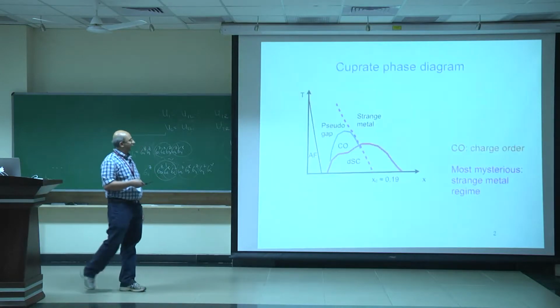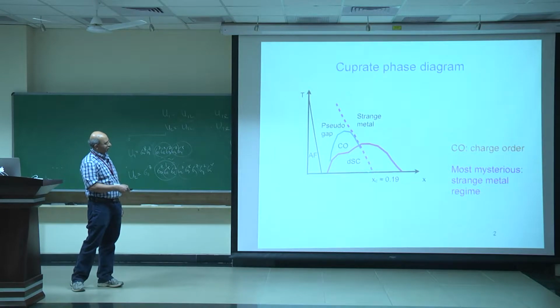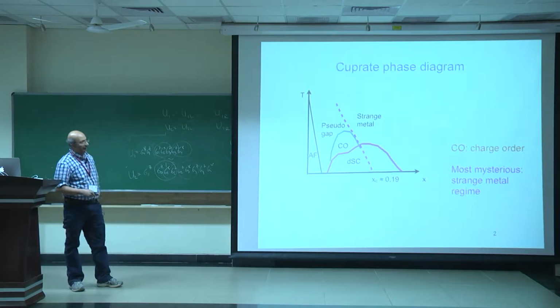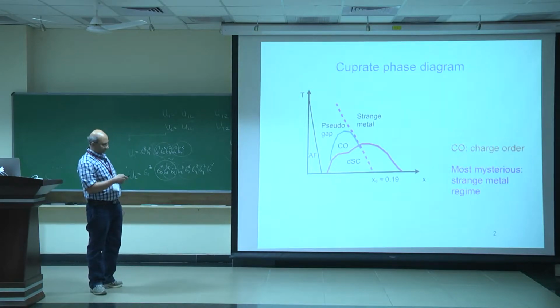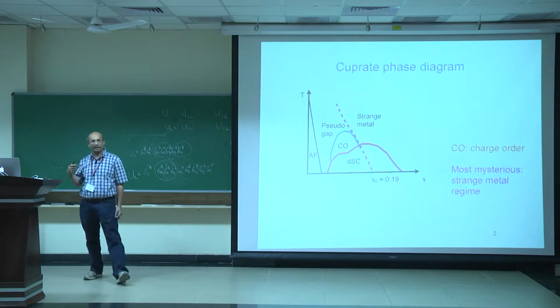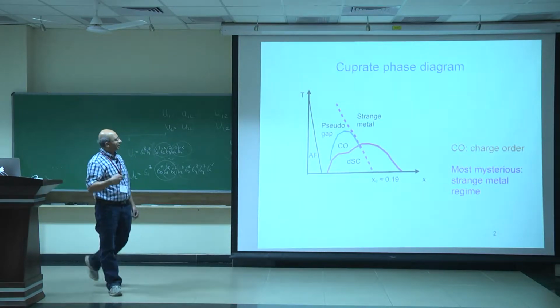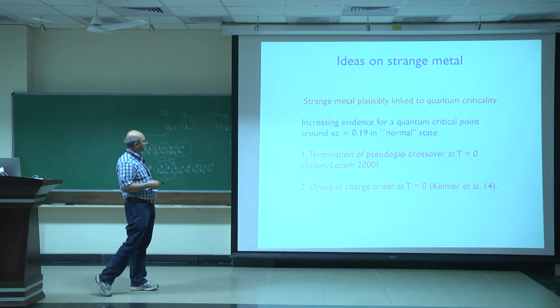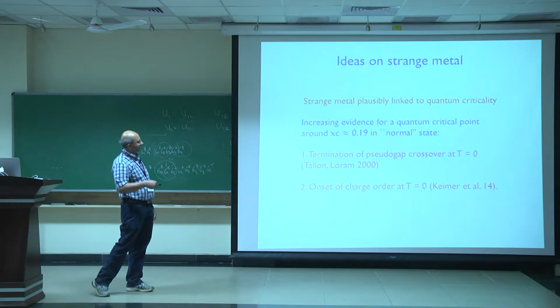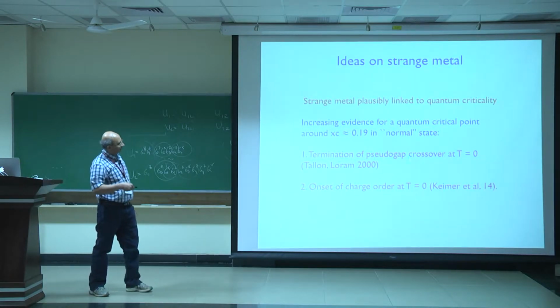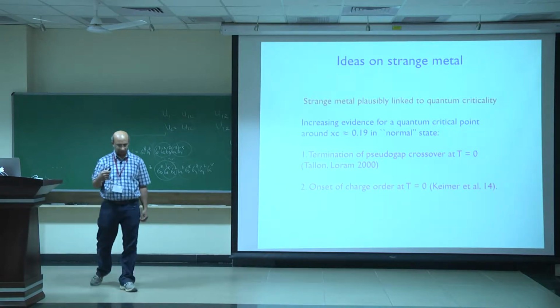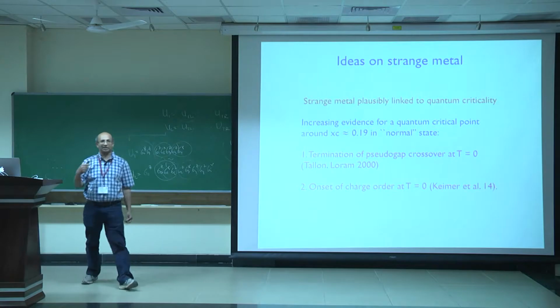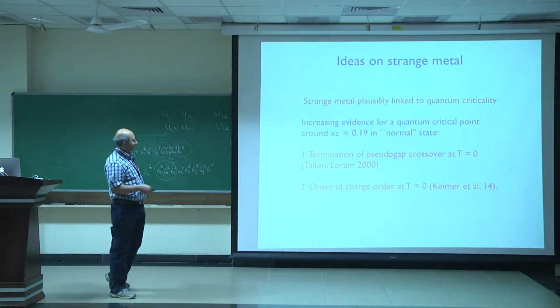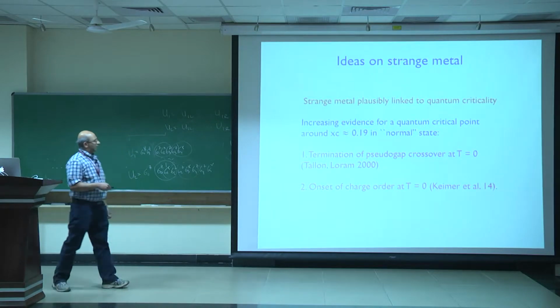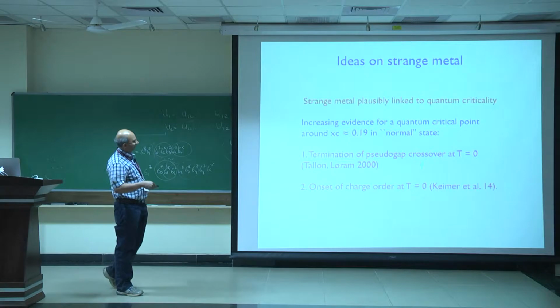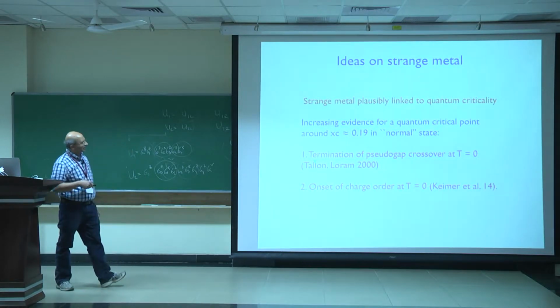So there's increasing evidence in the phase diagram for something special happening at a critical doping of about 19%. This was suggested, I guess, about 15 years back through an analysis of thermodynamic and transport experiments by Tallon and Loram. They pointed out that the famous pseudogap crossover, which occurs at some finite temperature in the underdoped samples, if you extrapolate it, terminates at zero temperature at a critical doping of about 19%. And in the years since, this seems like a not crazy thing to say. It may actually be a reasonably correct statement.